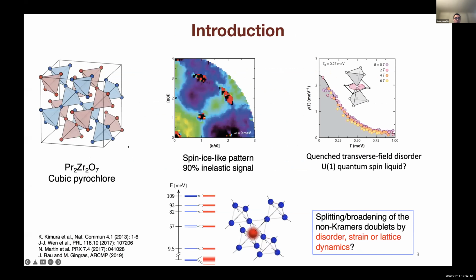The material we studied is praseodymium zirconate, which is a cubic pyrochlore, where praseodymium and zirconium ions sit on two interpenetrating sublattices of corner-sharing tetrahedra. The spin ice-like pattern was previously revealed by quasi-elastic neutron scattering, and significantly more than 90% of the neutron scattering is inelastic, which provides evidence for quantum fluctuations. But what distinguishes praseodymium zirconate from other pyrochlores is the presence of structural disorder, even in